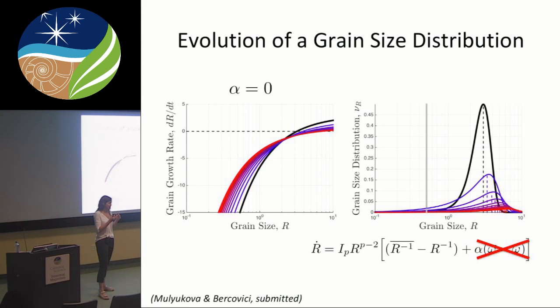But let's say, one of my colleagues, Jennifer Girard, does deformation of MgO or even olivine orthopyroxene systems. You look at your sample from a TEM or SEM, and you look at all your grains, and you try to deduce your 3D structure just from looking at this 2D plane. And depending on the stress, you'll have some prevalent grain size. Ultramylonitic conditions, typically somewhat higher stresses, would be from a few microns to a few tens of microns. This would correspond to stresses that will depend on temperature, of course. How broad it is depends, again, on stress. So it can vary anywhere from a few microns to tens to hundreds of microns.